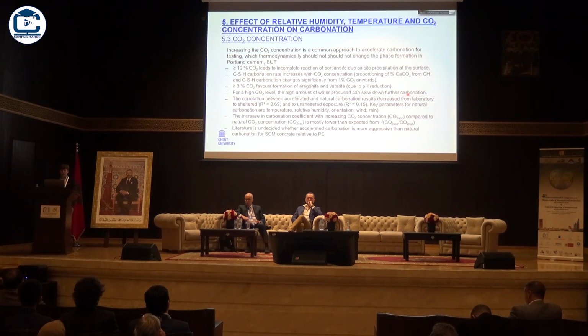So it's not always easy to correlate accelerated tests to natural conditions, because in natural conditions, certainly if it's unsheltered, you have rain. And rain means again saturation of the surface layer, so a huge decrease in the carbon dioxide ingress. So they found in reality the relation between lab carbonation rates and the ones you find in unsheltered condition, an R square of only 0.15, which is quite low.